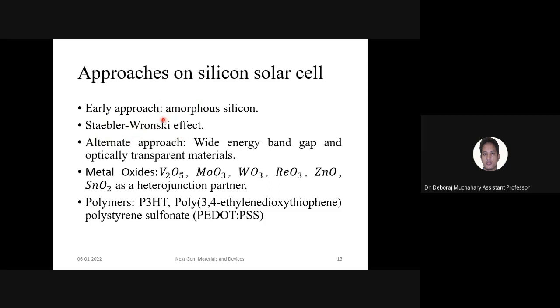Due to that problem, investigation of other materials as a partner to the silicon has been going on. There are different approaches, like what we need is a wide energy band gap. Why do we need a wide energy band gap? Because when we expose light to the solar cell, the front layer should pass the light, and almost all the visible light needs to fall on the surface of the silicon lying underneath. Silicon has a good absorption coefficient over a wide absorption range. So if we keep a wide band gap material on top of the silicon and the light is allowed to fall there, the absorption of that light will be more effective. That is why wide band gap materials that are optically transparent are searched for.